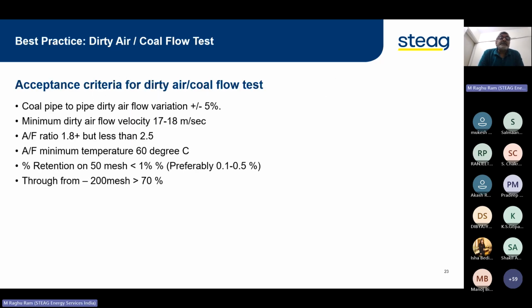Just criteria for acceptance is coal pipe to pipe dirty airflow variation cannot be more than 5%. Minimum dirty airflow velocity should be around 17, 18 meters per second. Air fuel ratio to be 1.8 plus, but it should be less than 2.5. Minimum temperature, depending on the volatile matter, should be 60.